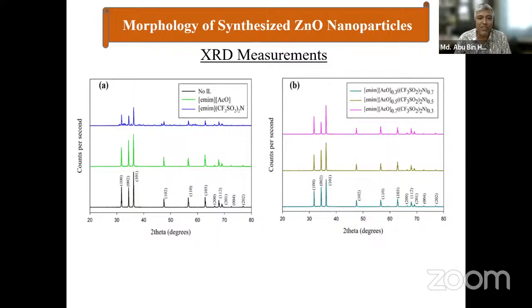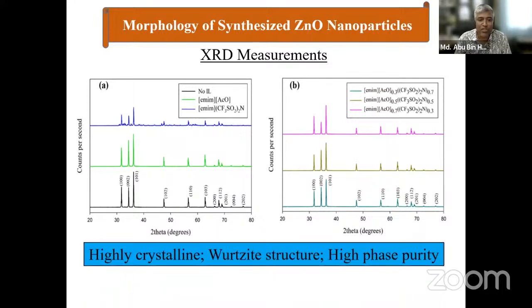So then we check the XRD measurements also. And XRD measurements show that these are highly crystalline. Wurtzite structure is here, and they have high phase purity. Here is no ionic liquid, single ionic liquid, and here we can see the double salt ionic liquids, so this crystallinity is retained.